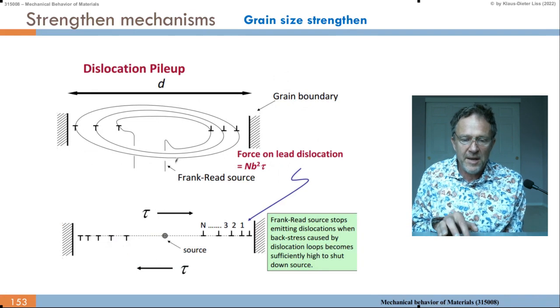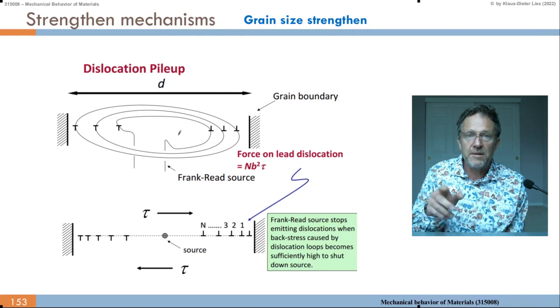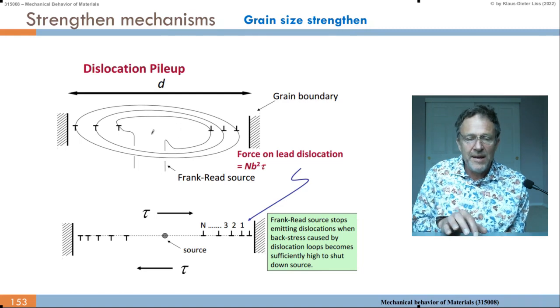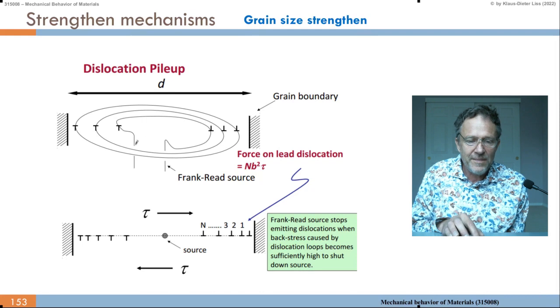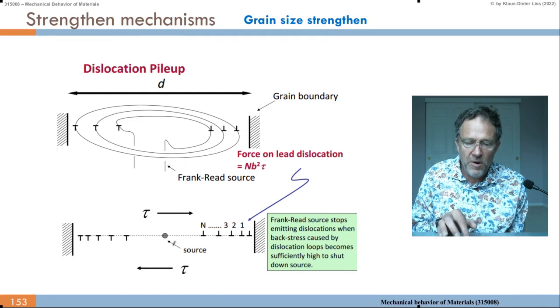I mentioned there's a Frank-Read source. So Frank-Read source, I've shown this schematic movie where you create a dislocation loop. It may go down somewhere or it may be pinned to something. And then it increases, and in the next cycle it increases further. Eventually these two parts grow together, and we have one loop here in the plane. Then it increases, and as these dislocations now move towards the grain boundary, they pile up, as demonstrated here again.